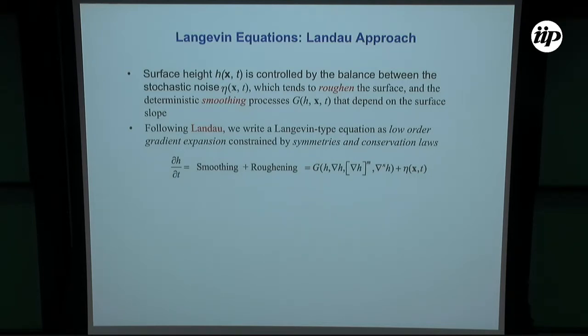So how do we study this kind of system? Well, we already said that the system has scaling properties. So one of the best ways to look at a system like this is to use a Landau approach. Landau says that if you have a system that has scaling properties, when you write down a theory, you have to write down all terms of the same magnitude, because they have to scale the same way. If I call the surface h of x and t, when I look at how the surface evolves with time, I have to write down a balance between smoothing and roughening processes. The roughening process in thin film growth is the noise that comes from deposition. Deposition is random, so we have a random noise due to deposition. That roughens the surface.